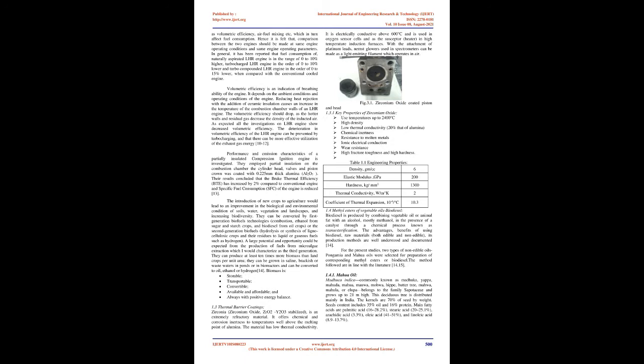7. A single-cylinder diesel engine with Superni 90 coated piston top and cylinder liner, which had a maximum engine power of 3.68 kilowatts and a compression ratio of 16:1. They used raw jatropha and pongamia oils and esterified jatropha oil as fuels. They found that the performance of the LHR engine improved, nitrogen oxide, NOx, levels decreased and exhaust gas temperatures increased with all three non-edible vegetable oils in comparison with diesel fuel. They also found that the combustion parameters of the non-edible vegetable oils were within reasonable limits and revealed that non-edible vegetable oils can be successfully utilized as substitute fuels in a LHR diesel engine.